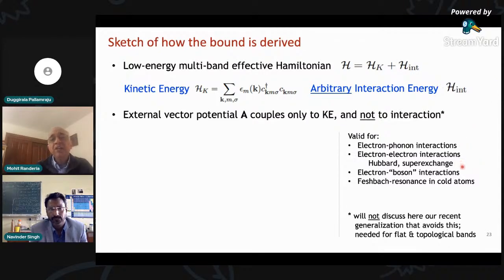This is certainly true for electron-phonon interactions. It's true for a wide range of electron-electron interactions, such as Hubbard superexchange, and a lot of electron-boson interactions. It's true for the Feshbach resonance in cold atoms. Is it always true? The answer is, if you have completely flat bands with no dispersion, or bands with a certain kind of topological character, then this could fail. Recently, we have generalized all the arguments that I'm about to present to those, but that would really take me into the realm of seminars. So let me not go there. This covers a very broad range of systems, okay?